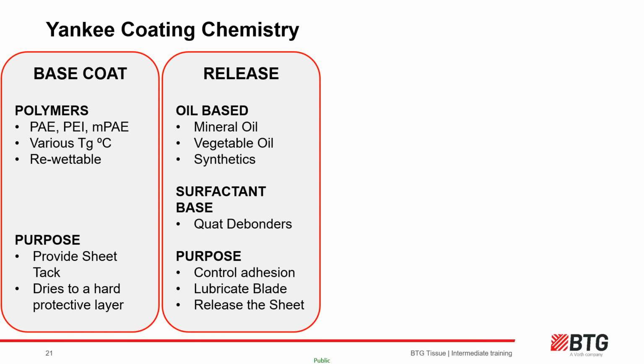The function of a release aid is to control adhesion by interrupting the adhesive network and suppress the glass transition temperature, thus extending the re-wetting window. Release also lubricates the blade, reduces blade friction against the coating layers, and then releases the sheet from the Yankee, helping to generate stretch as the release migrates to the sheet side of the coating over the Yankee cylinder.